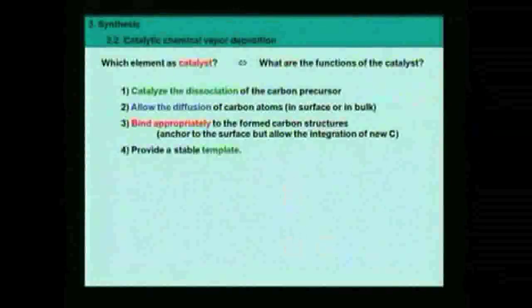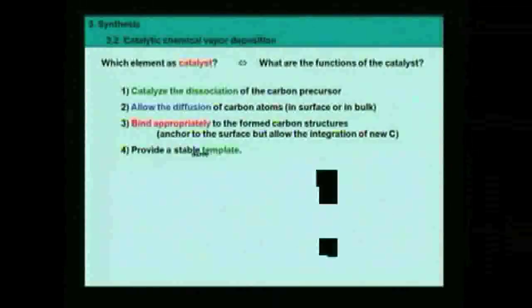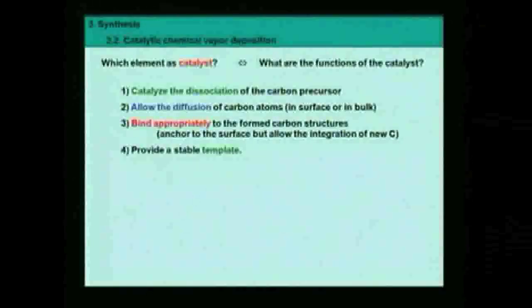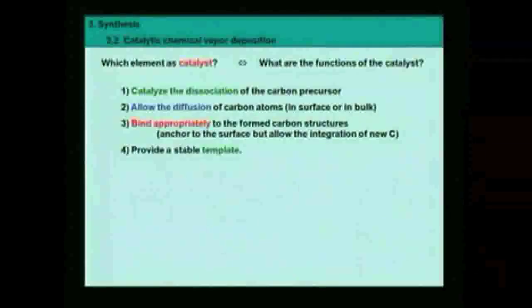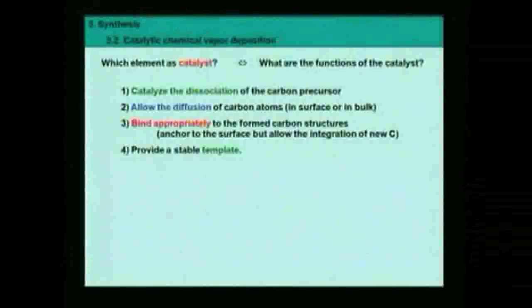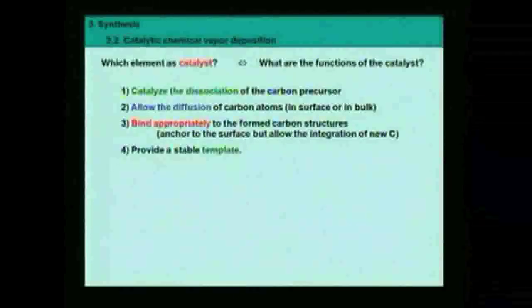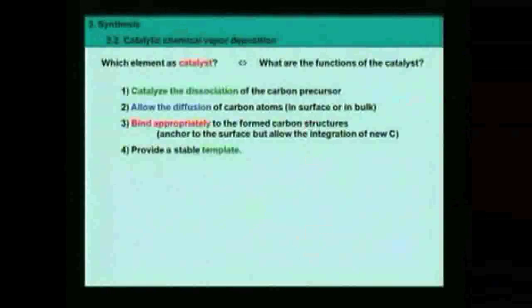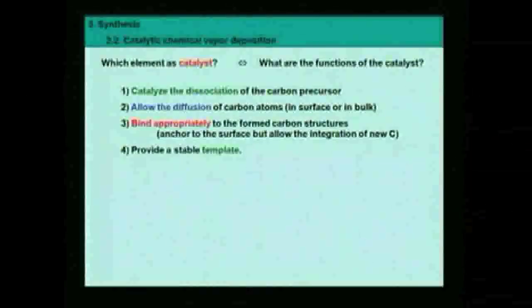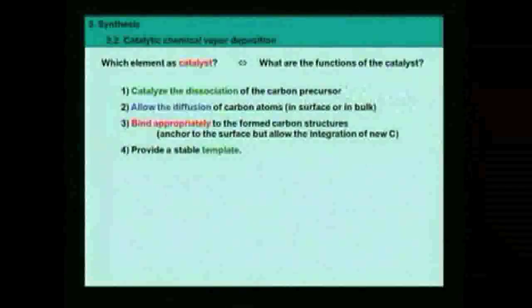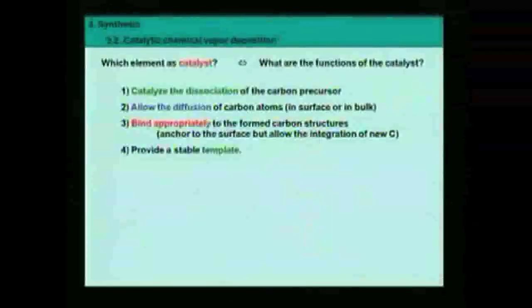Here we'll see that there is some deactivation of the catalyst for many reasons. But it's also the same in heterogeneous catalysis and homogeneous catalysis. Deactivation, poisoning is just a very general phenomenon in catalysis. So the answer is yes, it is a real catalyst, and the catalytic act is to assist the dissociation of the carbon precursor. This is why this is a catalyst. But it is not only a catalyst here. And this is the difference compared to heterogeneous catalysis, where you form gaseous or liquid molecules that will desorb from the surface. Here we form solid structures, and they stay on the surface. They are not desorbed. So you need other important functions for this element called catalyst.